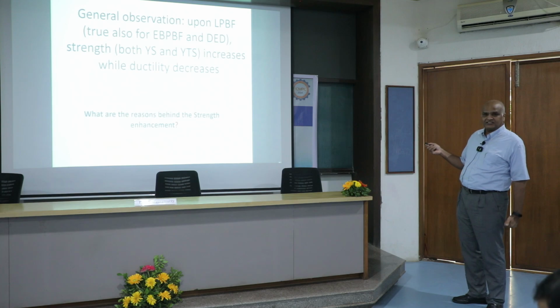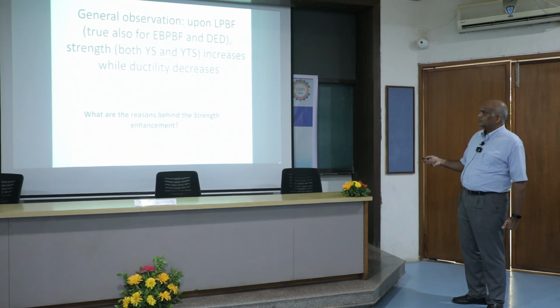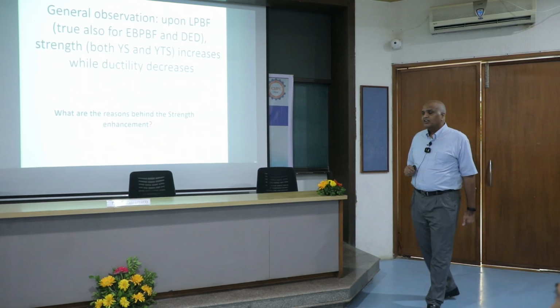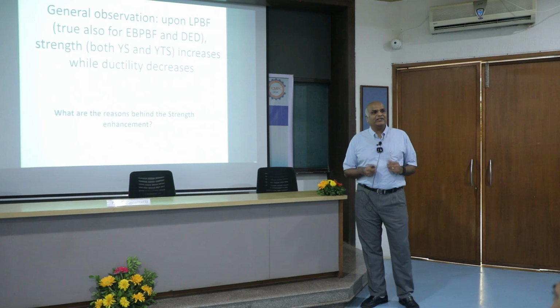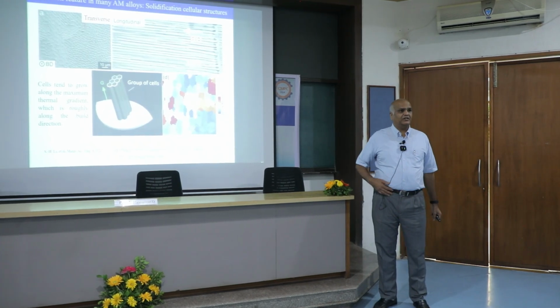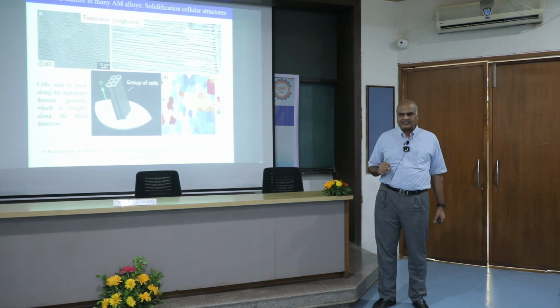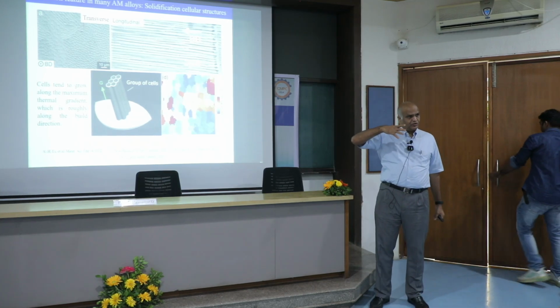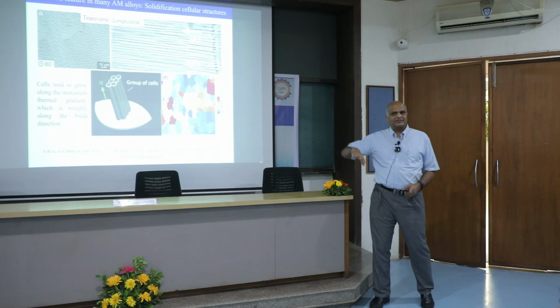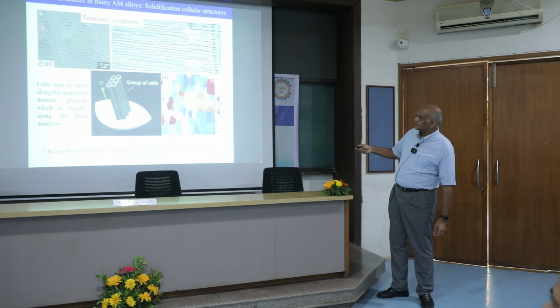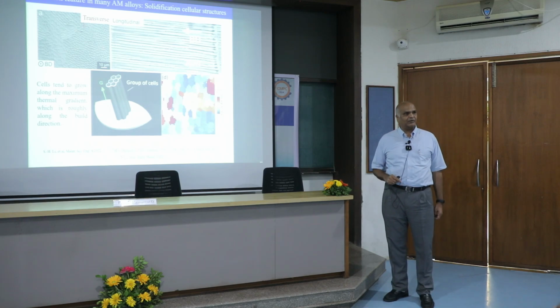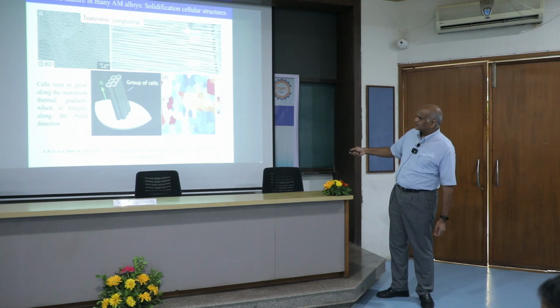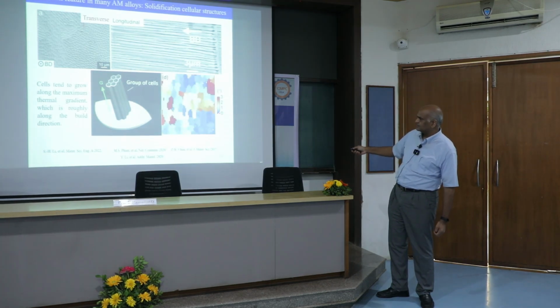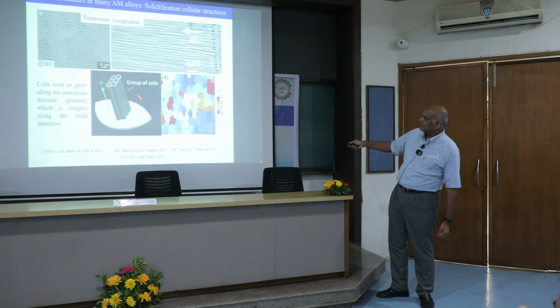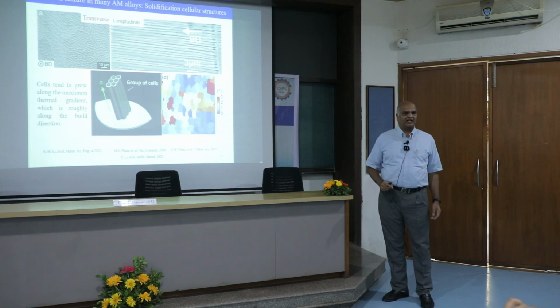Upon laser powder bed fusion, this is the 3D printing technique, but it's also true for other techniques, strength goes up and ductility decreases. Okay, what is the reason? So what is the microstructural reason? Now, metals, when they solidify, have dendritic solidification. But here there are typically rapid solidification conditions, and this is now deep metallurgy. What happens is you get these kinds of features: solidification cell structures come about. This is a schematic illustration, and the misorientation between these cells is very, very small, less than 3 degrees. If you look from the top, you see these cell structures, and from the side you see these are all cells that grow along the thermal gradient.